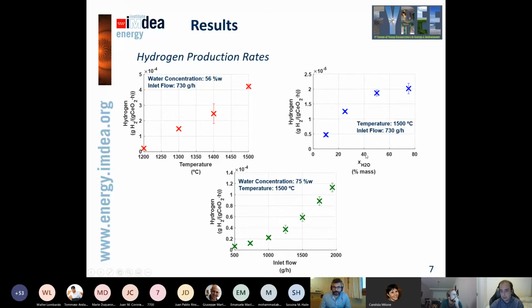In the case of the water concentration, we see something similar. Just taking a look at the equations that I showed before, the thermodynamic and the kinetic one, it just says that if we have more partial pressure of water, the kinetics will be a little bit faster.